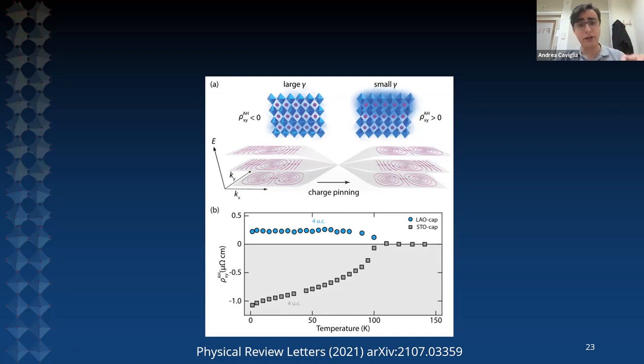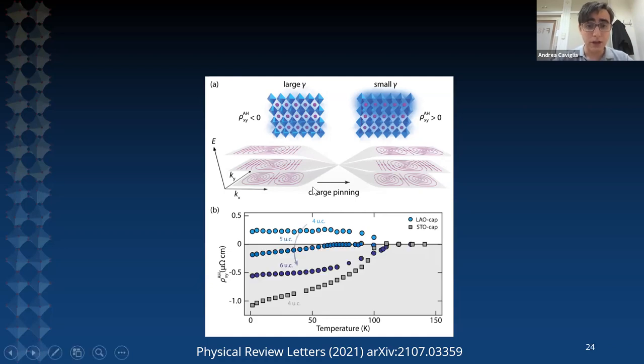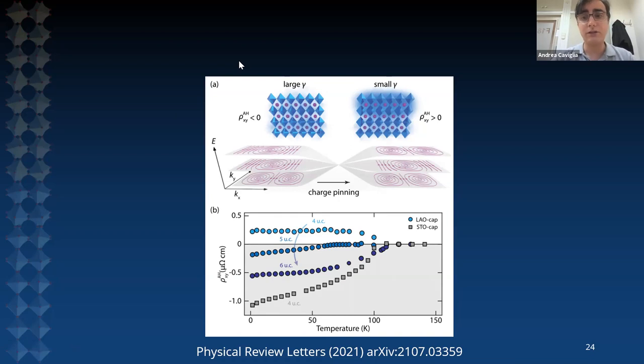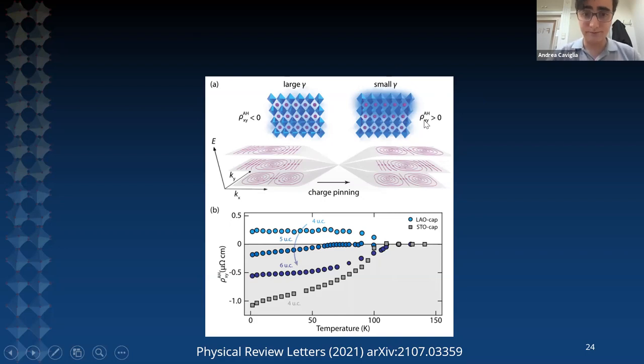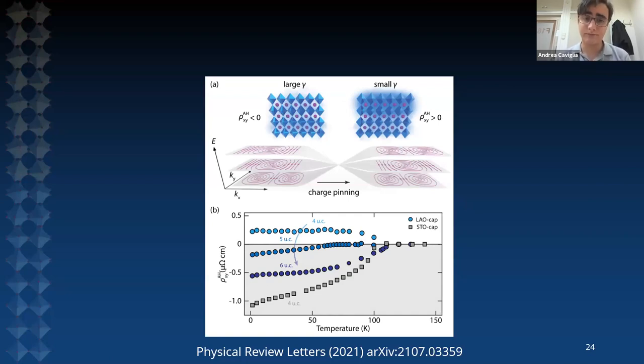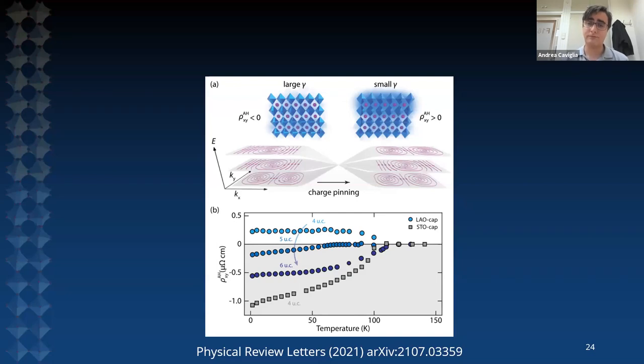This is a nice confirmation that we have coupled this charge reconstruction with the arrangement of topological charges in the system. If we make the strontium ruthenate layer thicker — instead of four unit cells, a much thicker layer — we gradually recover the bulk-like behavior. This is really an effect induced right at the interface. There are many different phenomena responsible for a change in the anomalous Hall effect: changing the Fermi level and rearrangement of the band structure. Charge transfer is one mechanism and it probably contributes to both.